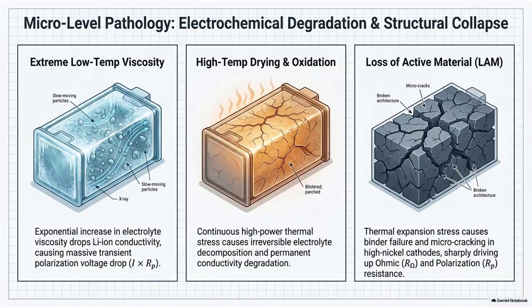Very. During aggressive cycling, the anisotropic volume expansion, meaning it expands unevenly, of the high nickel particles causes severe intergranular microcracking. The actual secondary particles fracture from the inside out. Wow, so they're shattering internally. And that exposes fresh, unpassivated cathode surfaces to the electrolyte, right? Which triggers violent localized side reactions all over again. Furthermore, this microcracking leads to transition metal dissolution. The nickel and manganese ions literally dissolve into the electrolyte, migrate all the way across the separator, and deposit themselves onto the anode. Oh man, which destroys that SEI layer we just talked about.